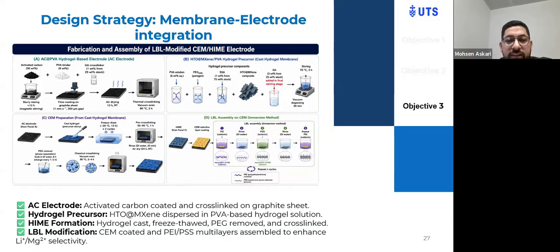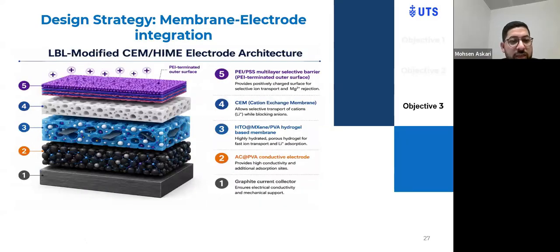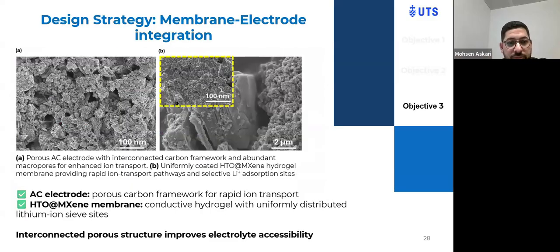After that, for use in MCDI, we put the cation exchange membrane laminated on top of these layers, and layer by layer with polyethyleneimine and polystyrene sulfonate, in which the outer layer is the positive layer. So we have this kind of structure: activated carbon based on the PVA, HTO MXene in PVA. These have a synergy because both of them are PVA and have a good lamination, the cation exchange membrane, and the LBL layer, where the outer surface has the positive charge.